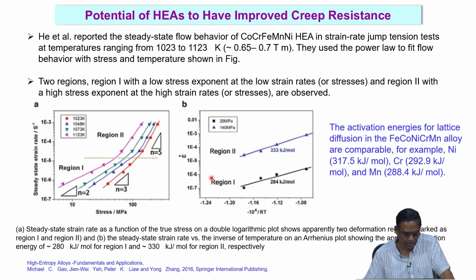What you are seeing here is the steady state strain rate as a function of true stress on a double logarithmic plot, which shows apparently two deformation regions marked as 1 and 2, and the steady state strain rate versus inverse of temperature on an Arrhenius plot, showing an apparent activation energy of 280 kilojoule per mole for region 1 and 330 kilojoule per mole for region 2 respectively.